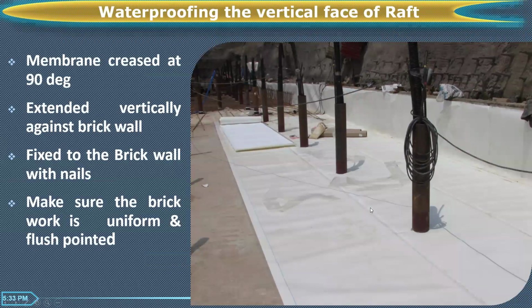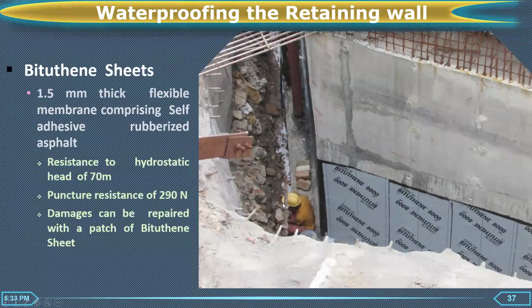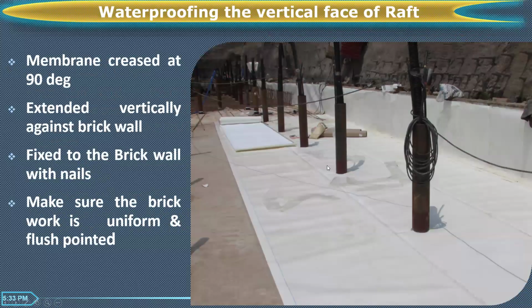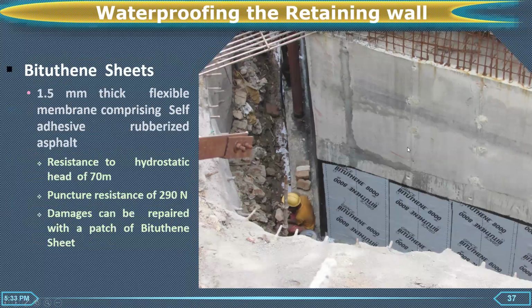You can see here the sheet. The white one is the sheet waterproofing layer, the SDP sheet, and the black one is the casing pipe. Wherever the casing pipe passes through the sheet, there is a profile cut. The sheet is profile cut at this joint. So this sheet is laid and is extended on the vertical surface also without any discontinuity at the corner. Similarly, you can see the vertical face of the retaining wall. And here the bitumen sheet is provided, which is also again self-adhesive.